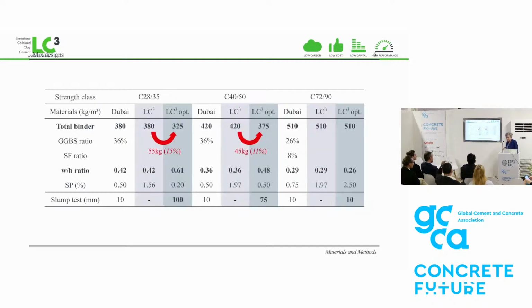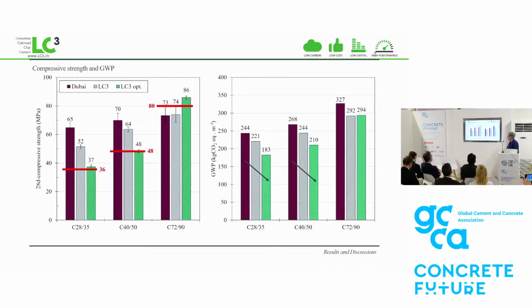expensive. So in the first step, we simply substituted all the binder content with LC3. But then we made a second step because we found that these concretes were respectively either over-designed or under-designed, so we wanted to better meet the strength specification, and there we could further reduce the CO2 footprint. So these are the results. You see on the left there the conventional concrete in Dubai now. You can see for the two lowest strength classes that these really exceed the design strength, which is not necessarily a good idea because then your reinforcement dimensioning is wrong. And for the highest strength grades, they weren't meeting the specification.